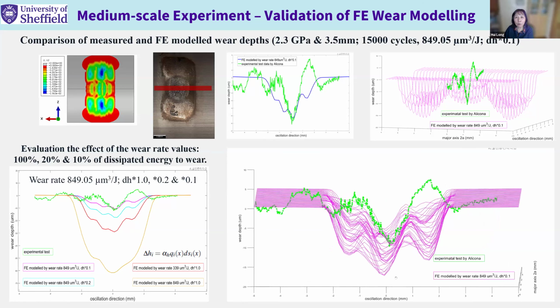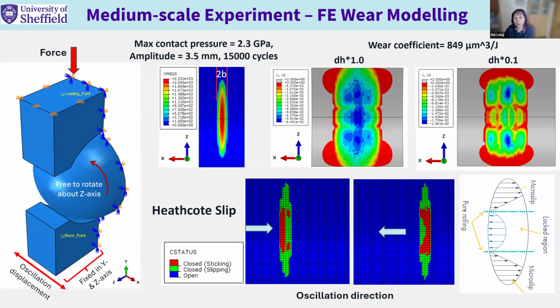So another important observation is, when you see this contact stress distribution pattern and also the wear pattern, we see the wear is also significant in this diagram in the top and the bottom regions, where the contact pressure is not highest. This is because it's the Heathcote slip.